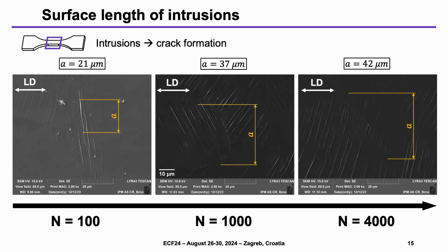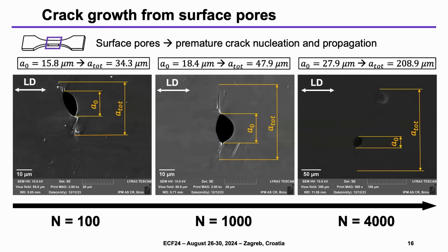However, at the same time, we also observe some surface cracks, which start from surface pores. And again, here we measure only the surface length of these cracks. As you can see here, the surface length is definitely higher than that of the intrusions, and it ranges from 35 to 210 microns. So we can say that for the additively manufactured materials, the crack starting from surface pores is a more detrimental damaging mechanism.